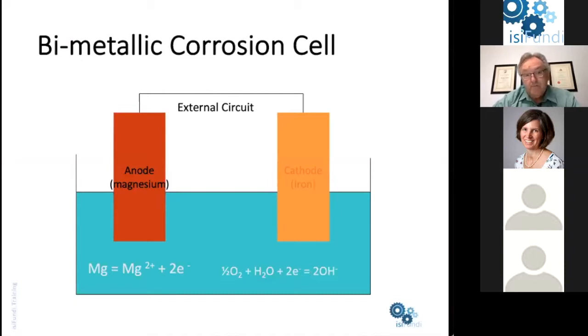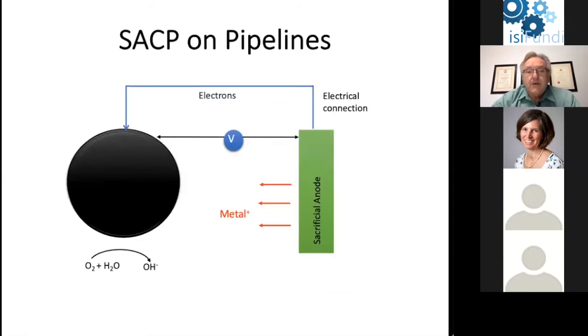And you'll notice that the anode in this case is magnesium. And if we were to go back to that table of the various materials that are anodic to steel, we'd see that magnesium is the one that is the most active. And the reason why we use magnesium is because it has a high driving voltage in order to provide the current to protect the iron. So in the pipeline situation, then, we have the sacrificial anode that is buried in the ground adjacent to the pipeline. It is physically connected with a cable. The electrons flow through the cable, the metal corrodes, and the pipeline is protected.